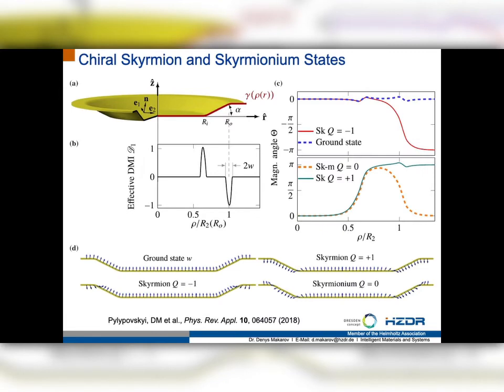For example, if you extend the system from, let's say, a quasi one-dimensional parabola to the simplest curved two-dimensional object, or three-dimensional in this case, where you have a plate-like geometry with, let's say, two bands, you will obviously expect to have a pinning of magnetic domain walls exactly at these bands. You have in this geometry two bands, so you will have two domain walls which can be supported in the system, or zero domain walls or two domain walls.